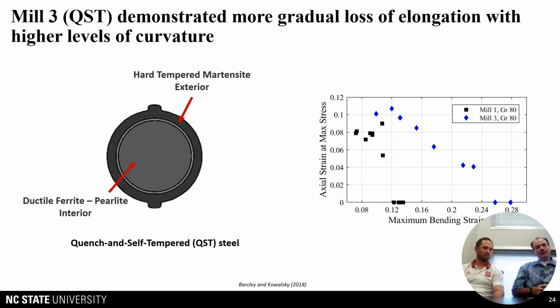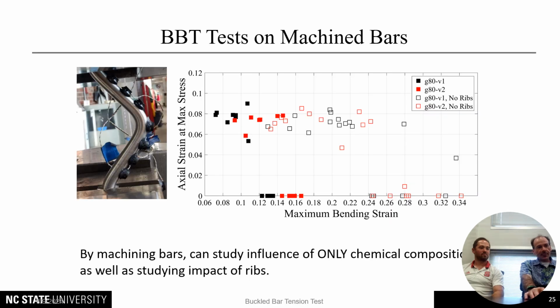And then the quench and self-tempered steel. The process, maybe we don't need to get into it now, but the process was different in terms of how it's produced, not by microalloying or adding different small alloying elements, but rather by a manufacturing process. You saw a different behavior in the BBT test, right? You could see the black was the microalloy and the blue was quench and self-temper, so it was much more gradual, not as abrupt a drop off. Exactly. It wasn't such an abrupt change. And that led us to, not to say, we always are mindful that there are many different ways to produce steel and there's not a right or wrong way, but you get different behaviors, and this could be an interesting behavior that could be beneficial.